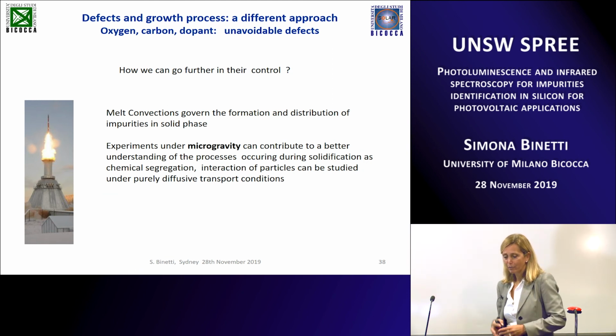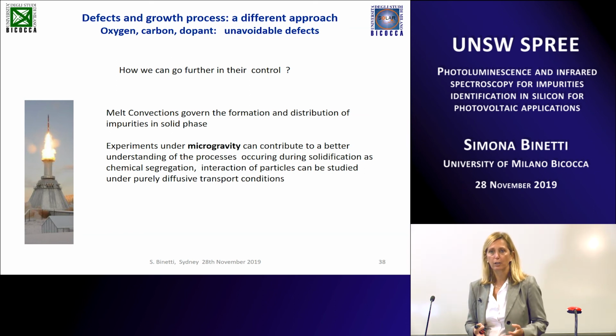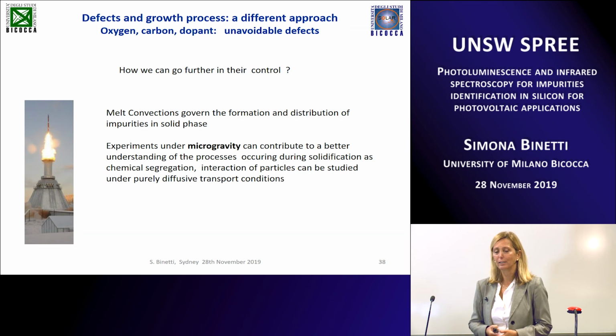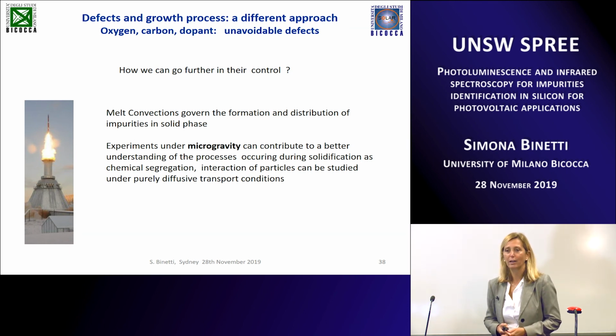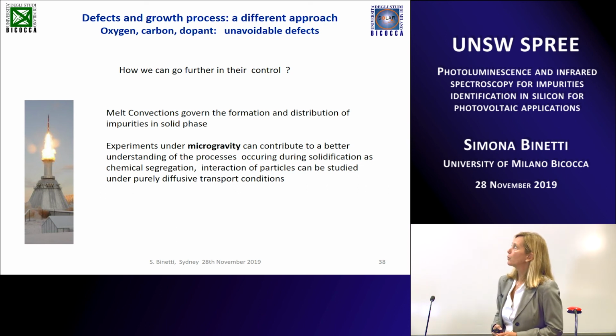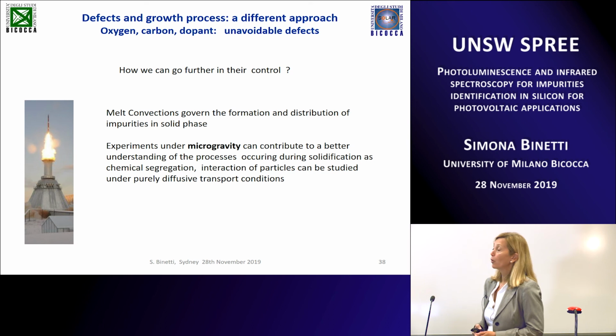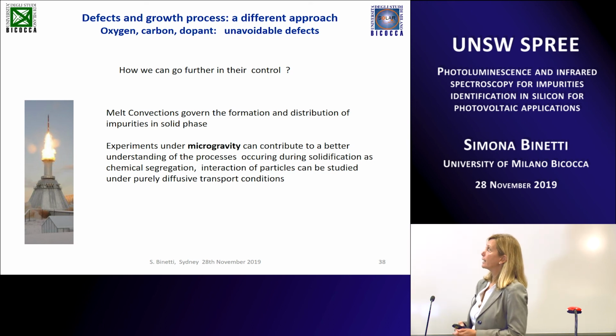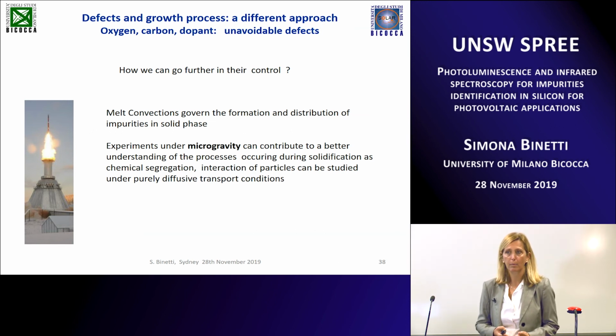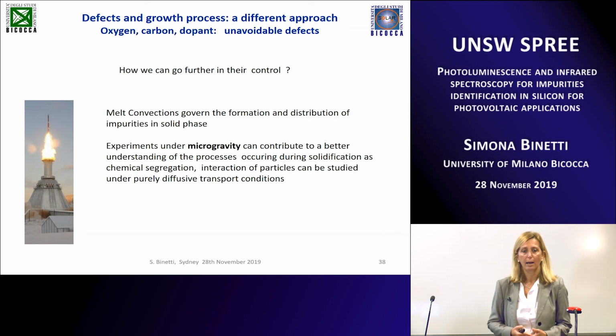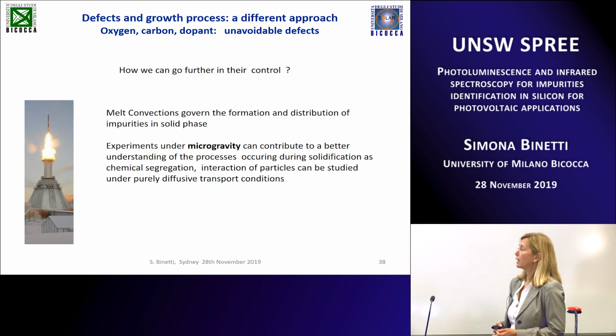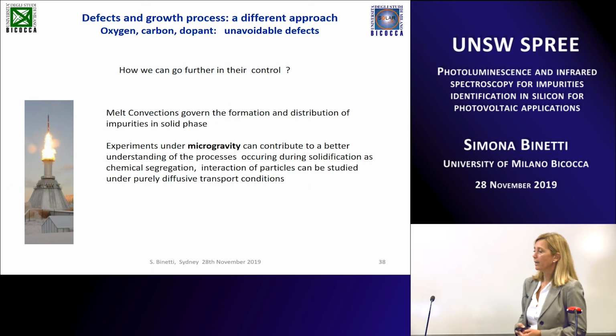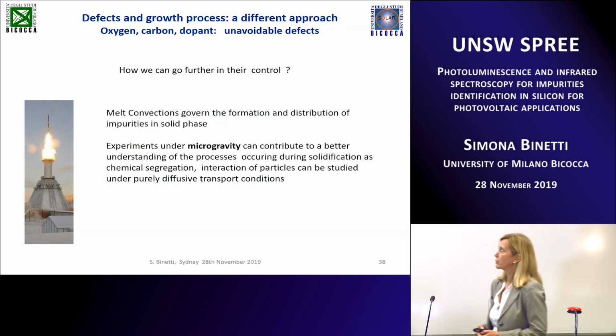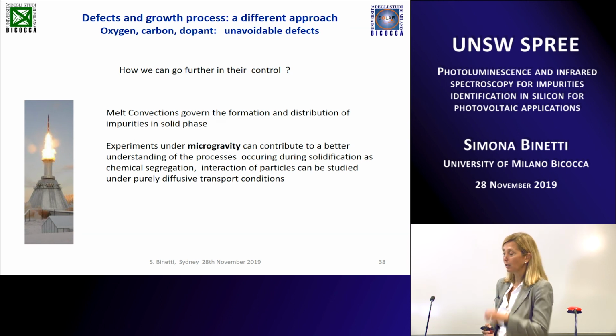Now I will just very briefly describe a completely different approach to studying oxygen and carbon in silicon, which for me was very nice and very interesting. I had the opportunity to work in performing experiments under microgravity, and the idea is how we can go further in the control of oxygen and carbon processes, and how we can make a new defect engineering of these impurities that cannot be avoided in silicon, by studying the formation and the segregation of these impurities, because you know that these are related to the melt convections that govern the formation and distribution of impurities during the ingot growth process.